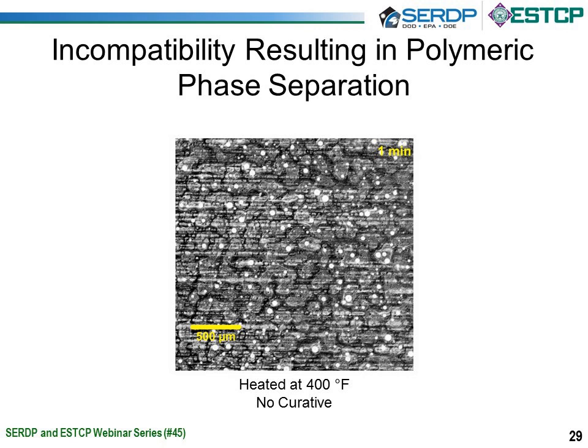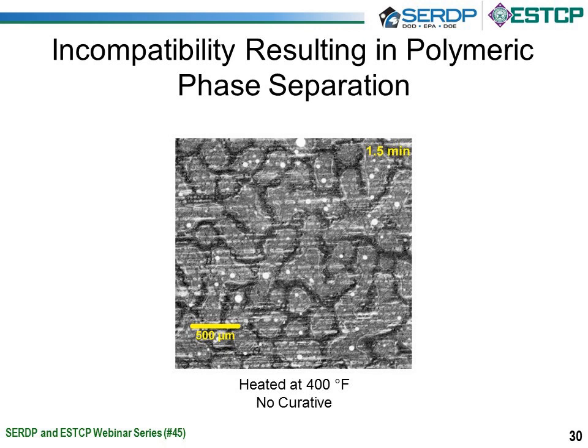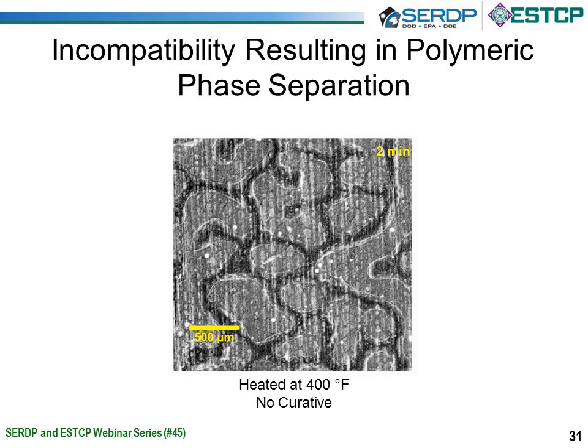I want to point out that the horizontal lines shown there are simply the aluminum panel onto which the clear polymer was applied, as these are optical images and we're able to see through the polymeric film. We know that these are polymer domains because the particle size that we applied as the powder through electrostatic application would be less than 100 microns, and as you can see from the scale bar, this is clearly much larger than that. So we are forming polymer domains. Slide 30 illustrates increased leveling and flow upon heating. This is at 1.5 minutes, and slide 31 is at 2 minutes.